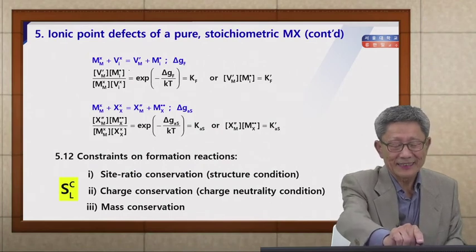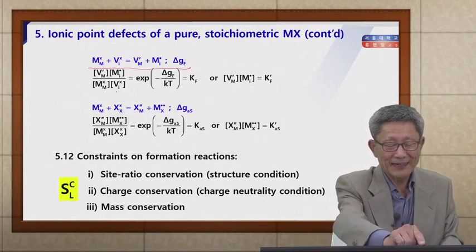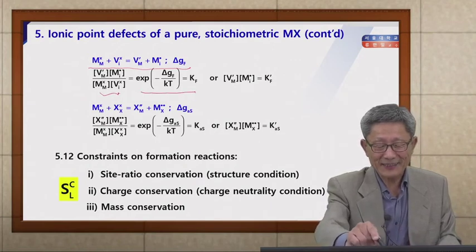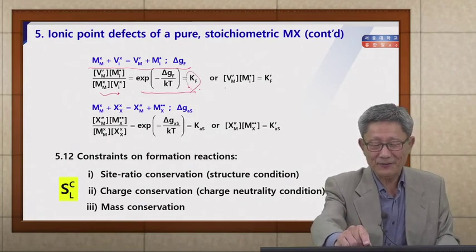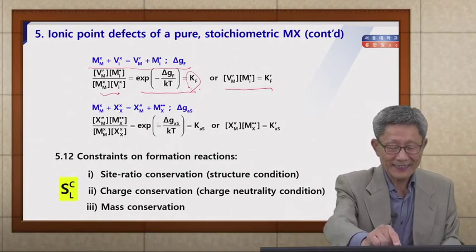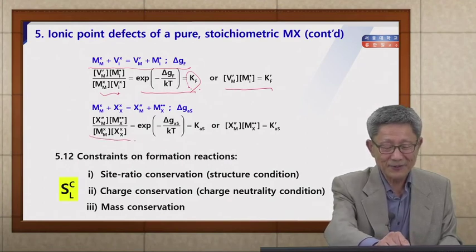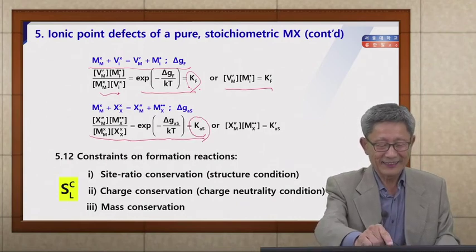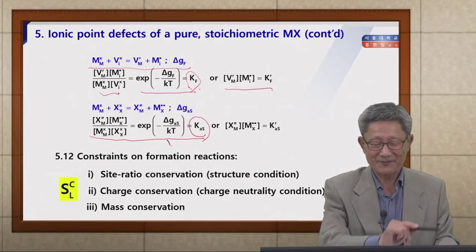Okay, so this is the Frenkel defect formation case. Now you can apply the mass action law, as before, to write down in this way. So this is called the Frenkel defect formation equilibrium constant. In defect chemistry jargon, you write in this way. And for the misplaced atoms, the anti-structure disorder or defect, again by applying the mass action law, you can write the anti-structure equilibrium constant in terms of the anti-structure defect formation Gibbs free energy this way.